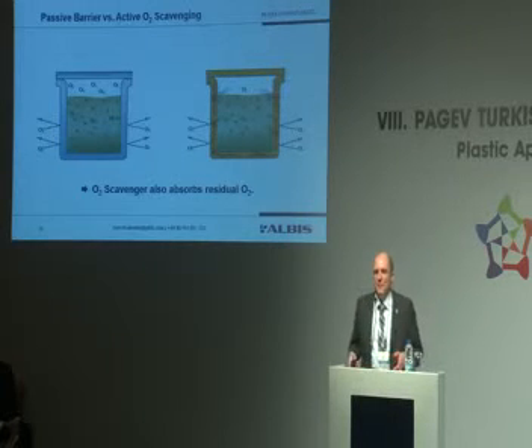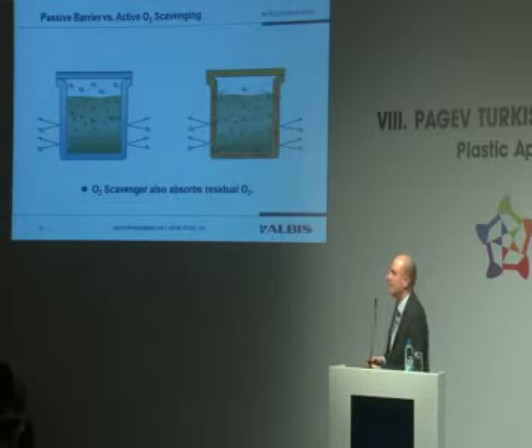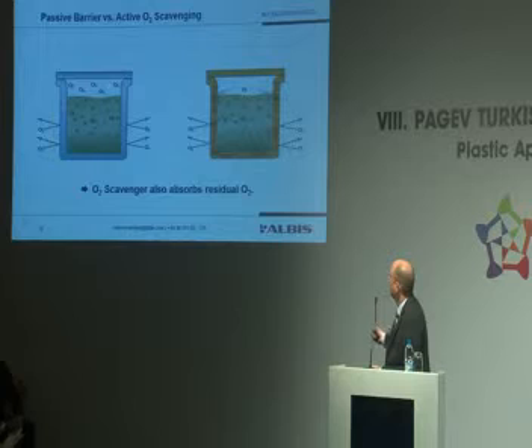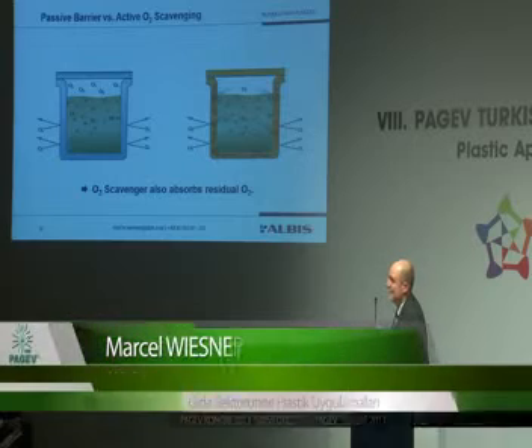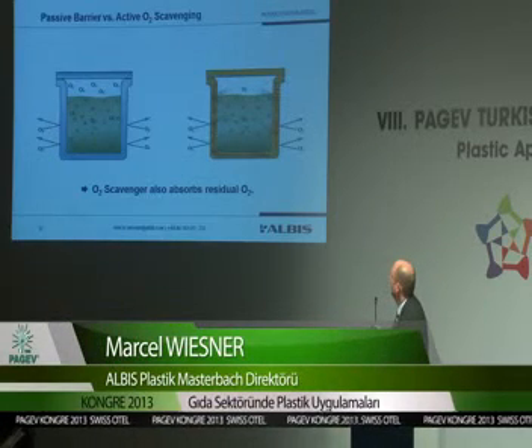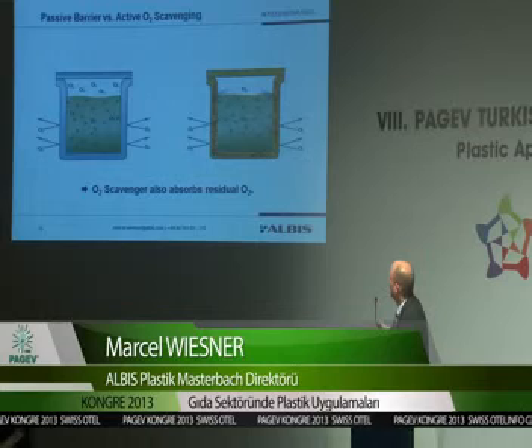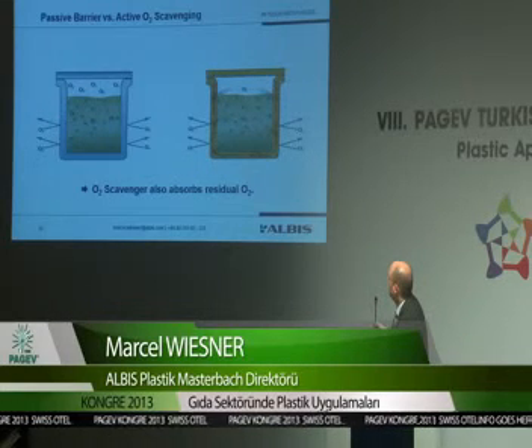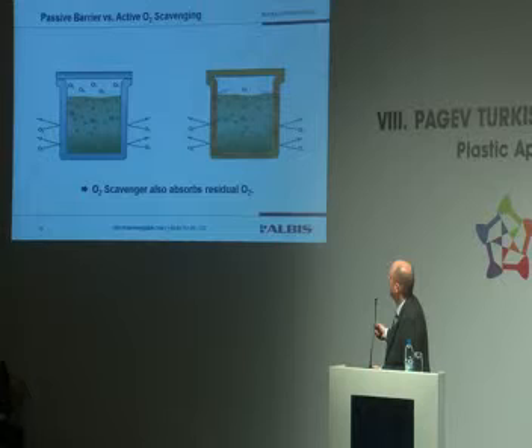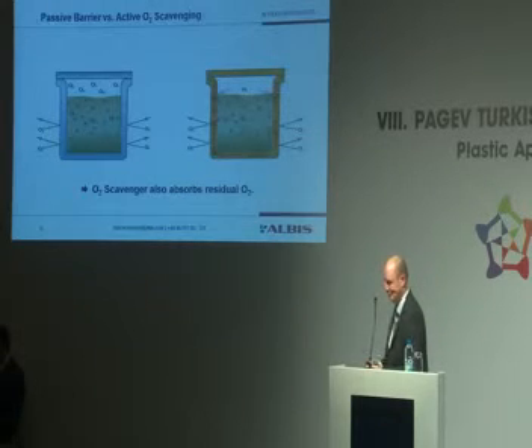Now, if you combine a barrier technology with an active scavenging technology, you have a slightly different picture. You still have your food packaging. The barrier blocks the oxygen from arriving inside the headspace of the packaging, but now, the scavenging effect would take oxygen through the thickness of the packaging film and absorb it internally. So after a certain period of time, and we will later on see how big this period of time is, you reduce the amount of oxygen compared to passive packaging.